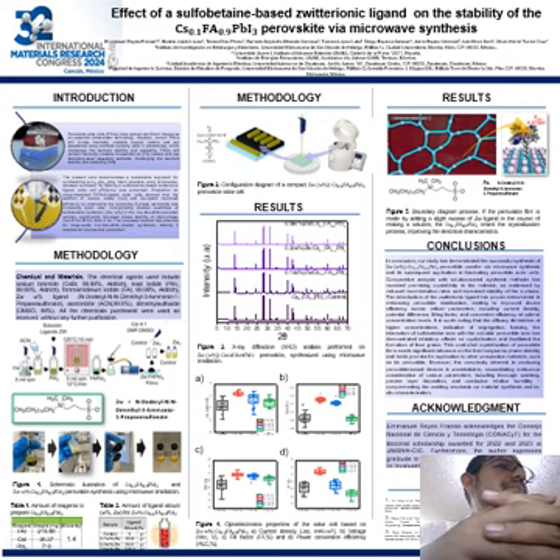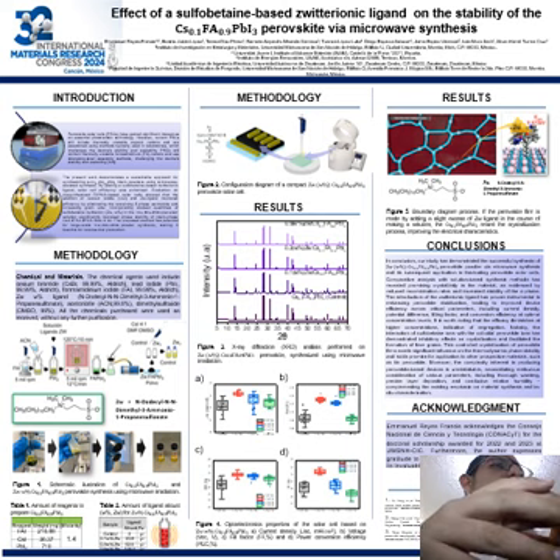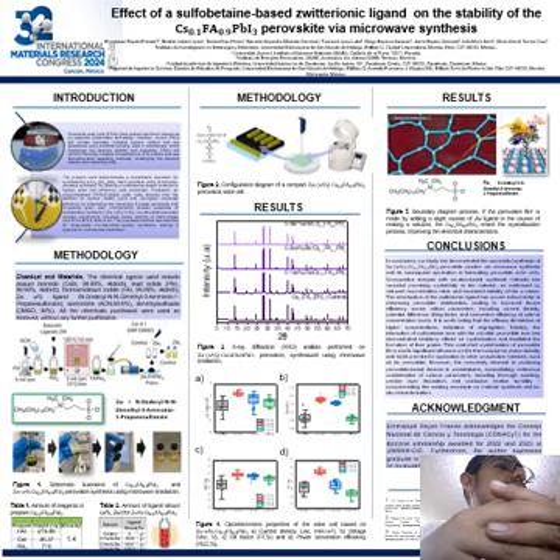And we proved that the zwitterionic ligand improves the efficiency of the device and eliminates the remaining undesirable delta phase perovskite, even increasing the grain size, because we can incorporate small quantities of this ligand, but significantly increasing the stability of the alpha black phase. The aim of this method is large-scale powder synthesis, making it feasible for commercial production.